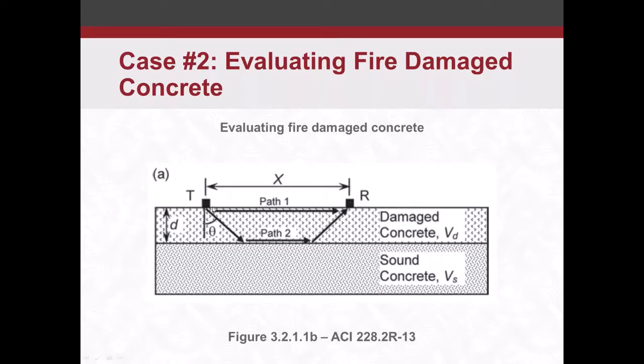As we increase our spacing, the travel time along the surface, because theoretically it's damaged, is going to have a lower wave velocity. So the faster wave speed is going to be traveling along the sound concrete underneath, and is going to get picked up by this receiver first. So eventually what we're going to see is our calculated wave speed is going to change.